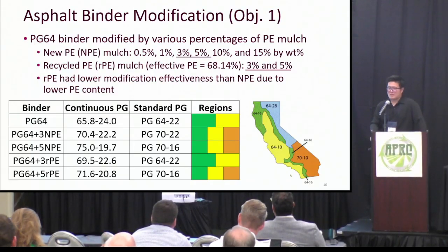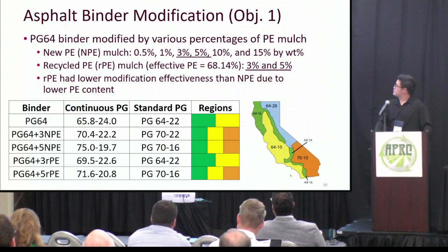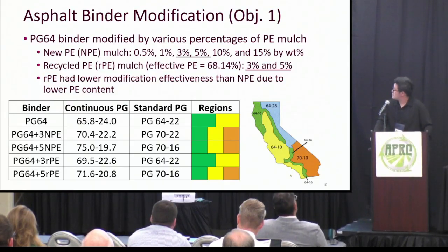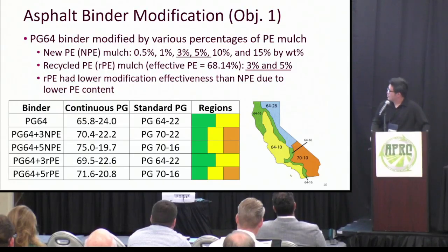And coming to objective 1, we use PG 64 as the working binder. We use new PE mulch and recycled PE mulch to modify the binder. Firstly, we use different dosages of new PE mulch to modify the binder, for example, 0.5%, 1%, 3%, 5%, 10%, and 15% by weight of binder. And the optimum dosages were 3% and 5%. And we use the same dosages of recycled PE mulch, 3% and 5%, to modify the asphalt.